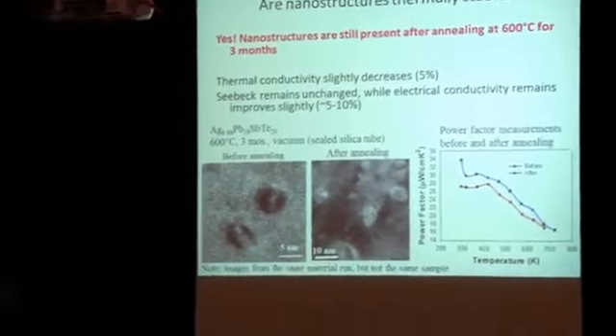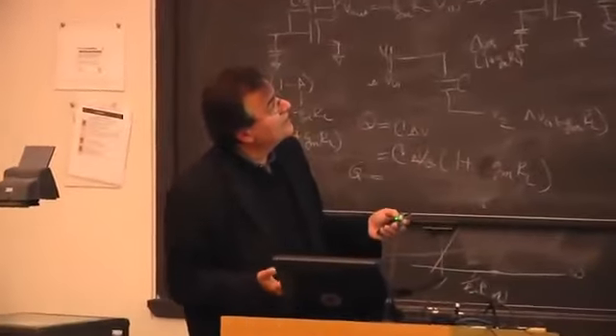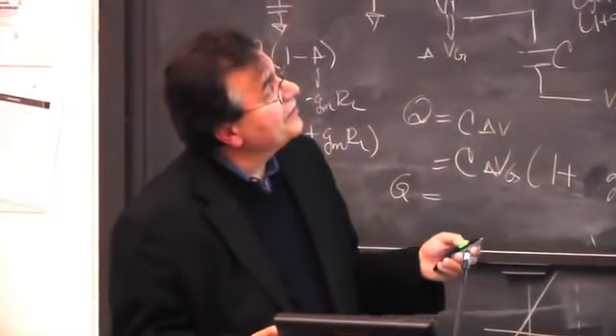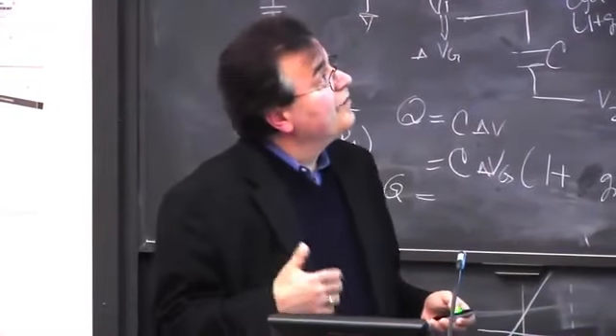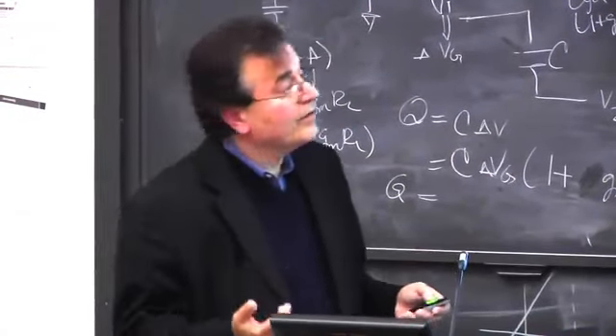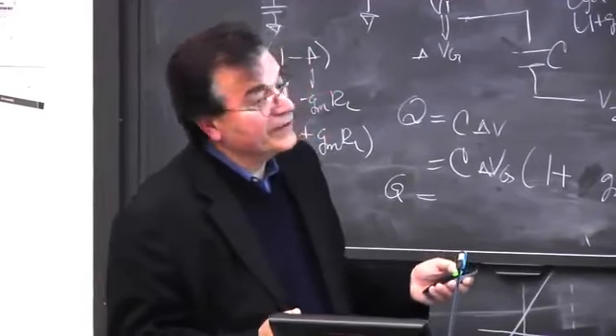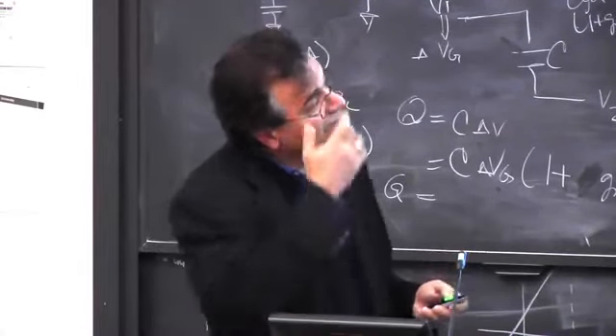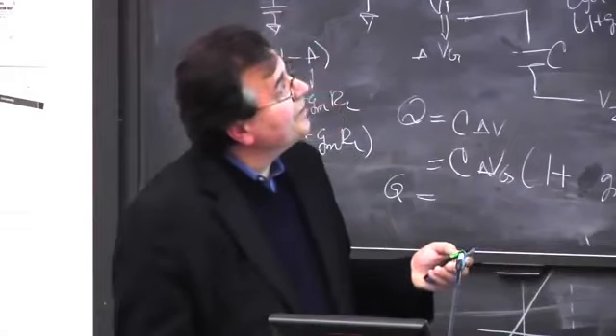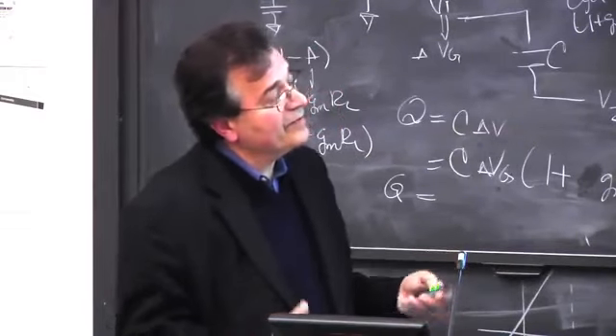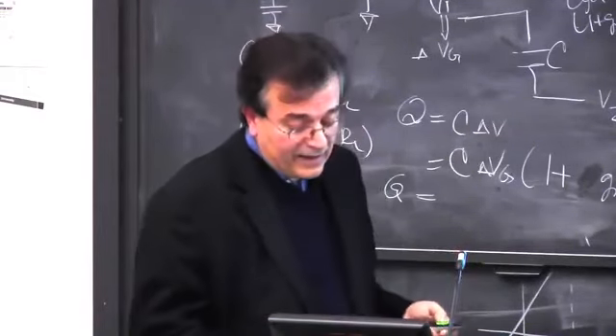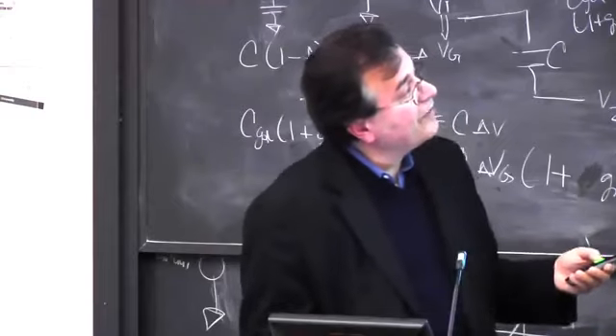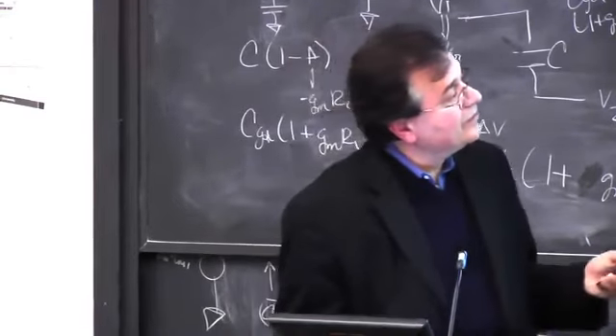Are they stable? Because they are thermodynamically driven, they are very stable. You can take these things and anneal them at 600 degrees for months. Not only do they not go away, you can examine the material before and after, and you find no difference. It gets better because you anneal out some of the other defects, and you get higher mobilities, and therefore higher power factors and higher ZTs. So they're very stable.